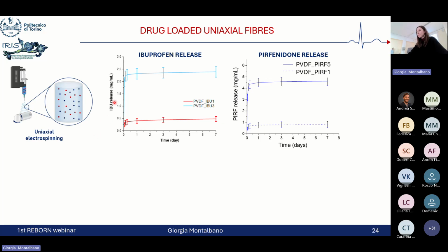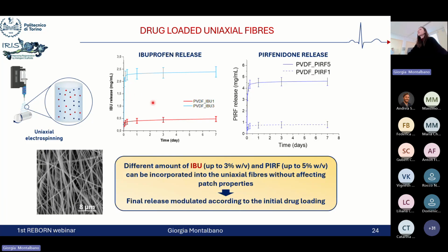So here, from the images representing the drug release test for both ibuprofen and pirfenidone, you can notice how we decided to test increasing concentrations of the drug in order also to define the highest concentration of both ibuprofen and pirfenidone that again could induce the preservation of all the other properties of the patch. And so it's quite evident also here from the release how this optimized methodology also supports a modulated release of the drug according to the initial drug loading.